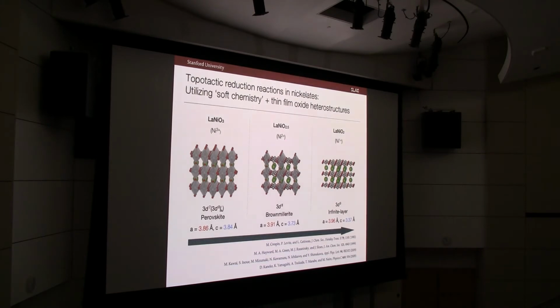So this small subfield was actually quite controversial. There were big problems reproducing this, and an important step was this group that showed that you could use metal hydrides to very reliably do this reduction chemistry. And for the work that I'm going to show you that we built on, also a key development in 2009 from two groups in Japan that found that you could do the same kind of reduction chemistries in thin films. And there are some advantages to doing that in thin film form that I'll tell you about.